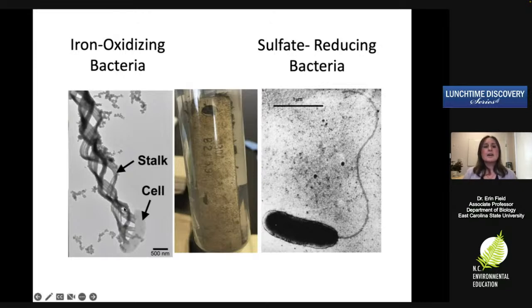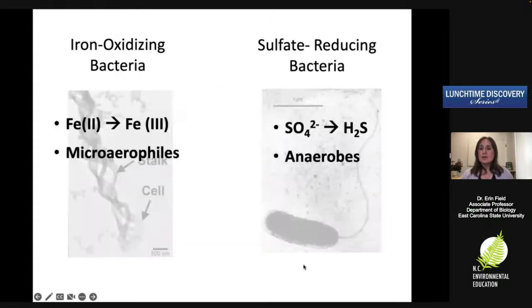So what you're seeing here is a photo of the iron oxidizers, what they look like, and sulfate reducers. This is one that we often see. And then what we did, in our case, we put out these little steel coupons. They're little pieces of steel. And you let the organisms colonize and start the corrosion process. And then we look at who's there. So we were able to isolate organisms from both. So we have iron oxidizing bacteria and sulfate reducers from the same steel coupon that we could study in the lab and ask, how do they interact?